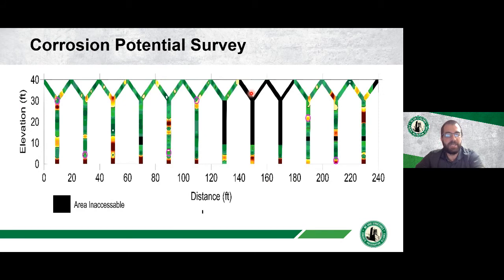So then we went and did corrosion potential surveys of the columns and beams and identified where those areas of active corrosion are. And you can see the yellow, the highlighted areas. These hot colors indicate where carbonation is a problem, and they're going to have spalling of concrete.